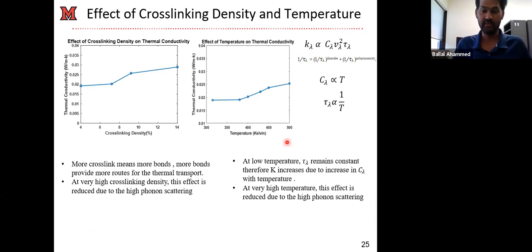So this is probably the last study we did on the thermal properties. Here you see we studied the effect of cross-linking density on the thermal conductivity. When we increase the cross-linking density, we found a slight positive trend. We found that it is increasing with the cross-linking density. But even at higher cross-linking densities, it gets saturated, and at even higher density, it will eventually reduce. The reason is that more cross-links mean more bonds, and more bonds provide more routes for the thermal transport. That's why at the beginning, when you increase the cross-linking density, the conductivity increases.